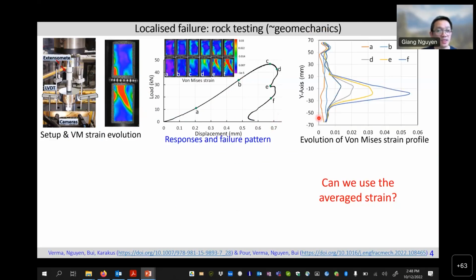We do the same thing, we plot the strain profile. We see that really after the peak here, the strain tends to intensify in the narrow zone here, and it's in this case one order of magnitude higher when it's close to fracture, shear fracture at the end, compared to the strain outside the red zone here.